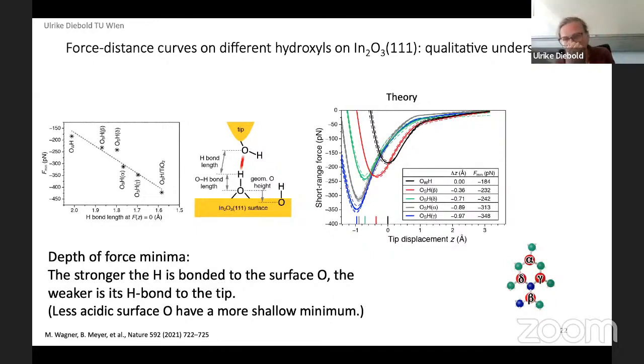So I should say that we control the tip and the distance so that we don't really take this proton off the surface. We just look at the formation of the hydrogen bond between the tip and the sample. If we go any closer, we often pluck this proton off the surface and then our tip changes. So we stay in this regime, and we don't go close enough to have this tunneling effect. What we haven't done, but could do, is repeat these experiments with D2O and see if there's any difference. I think it would be an interesting question, but we haven't done that. We really don't take the proton off. We just ask how it is related to the hydrogen bonds between the tip and the sample. That's really what we're probing.